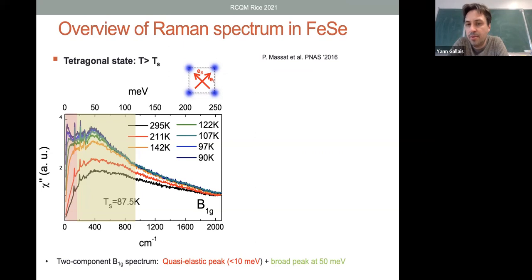So our interpretation is that it's a signature of this dual physics, both the itinerant and localized character of iron selenide. But one important thing is that this broader feature is not critical. So if it's really associated to local spins, it's not driving the nematic transition temperature. But it's very robust. It's seen at all sulfur content, so it's pervasive in the phase diagram. Okay.